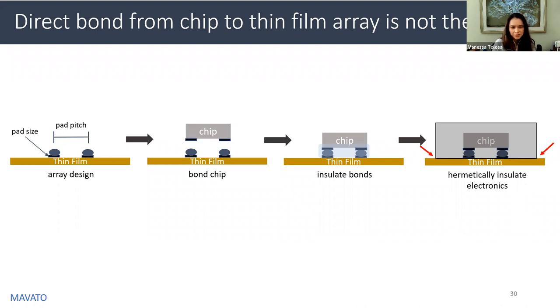So next, you flip chip bond the chip onto the thin film. And for that step, some of the knobs you can turn are the heating temperatures of the chip, temperatures of your substrate, the force that you're applying to make the bond, and the time that you are holding at each of these steps. So this step also can be its own project to develop, especially if you are now using non-standard bonding materials and substrates, which you will be if you're pushing design limits with higher channel counts. Anytime you're working on the edge of technology, you can't just send these out to vendors anymore. Almost every step here can be a PhD project. I think I've interviewed people who were getting their degrees in each of these areas.